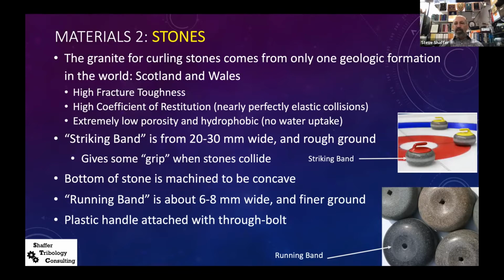And most modern stones have an insert in the bottom of the one type, and the rest of the stone is of the other type. And that's nice, because then these inserts can be changed to give the stones a longer lifetime. A typical curling stone will last 50 to 100 years in a curling club. You do have to sand them. You do have to texture the bottoms every season, or maybe a couple times a season, depending on how they're performing.